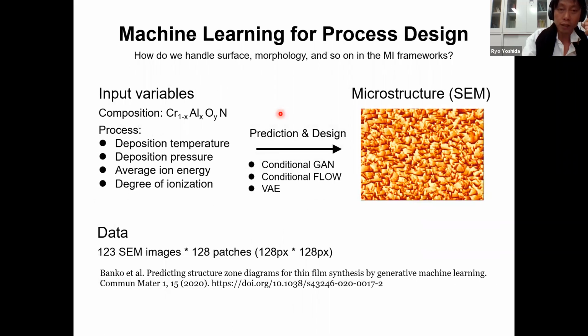Okay, so now let's see a specific example taken from this study. The input variable considered here is a 6-dimensional real-valued vector that consists of the 2 compositional parameters of the inorganic material and the 4 process parameters such as deposition temperature or deposition pressure and so on. This is a very important parameter for the sputtering of the thin film material. The output is a microscopic image of the microstructure of the material.